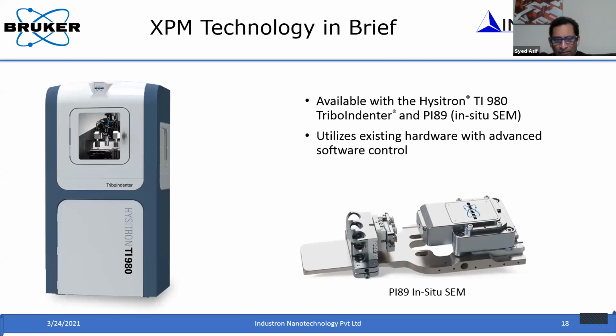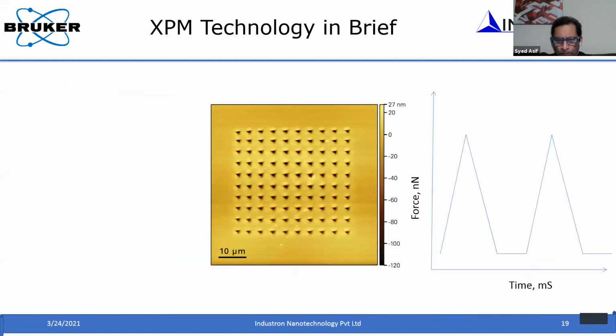And this can be done with our typical system like a TI-980 or in situ inside an SEM. And when you do it inside an SEM, there is an added advantage. For example, if you have EBSD or some other technique, you can correlate the EBSD map with the map that you get from this fast property mapping. So I have mentioned how you do this.